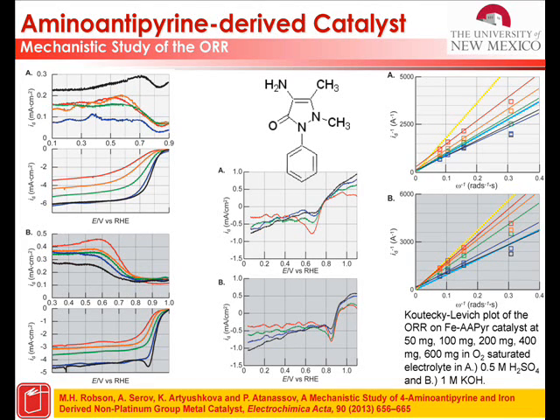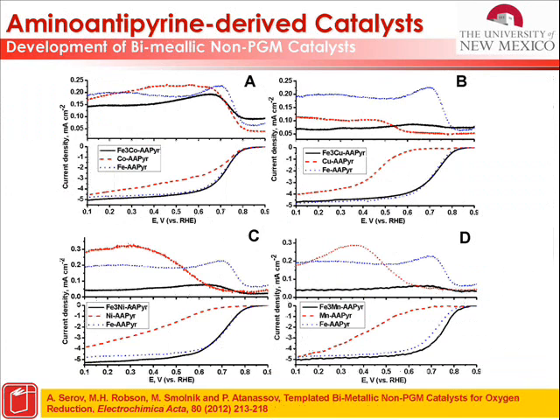You can make bimetallic and trimetallic catalysts this way, and in the case of manganese as a second metal, you introduce a very good catalyst to reduce essentially hydrogen peroxide locally. One of the most active catalysts is manganese oxide for hydrogen peroxide capture and reduction. And that catalyst immediately improves the performance.